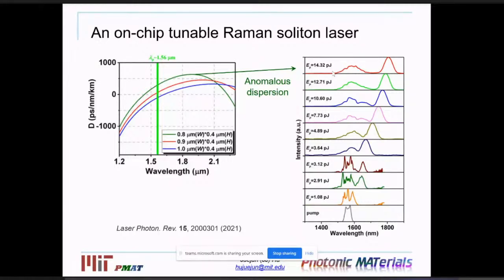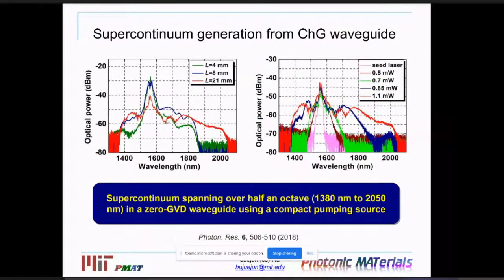Okay, so that's one type of light source, a tunable laser. Now, if you move on to this 0.9 micron waveguide, which exhibits zero group velocity dispersion, then instead of a Raman soliton, it triggers supercontinuum generation that covers a broadband. So this is what we did here. We used this kind of waveguide to generate a broad supercontinuum that covers from about 1.4 microns all the way to beyond 2 microns, a half octave spectral range, so it can enable broadband spectroscopic interrogation of photonic sensors.